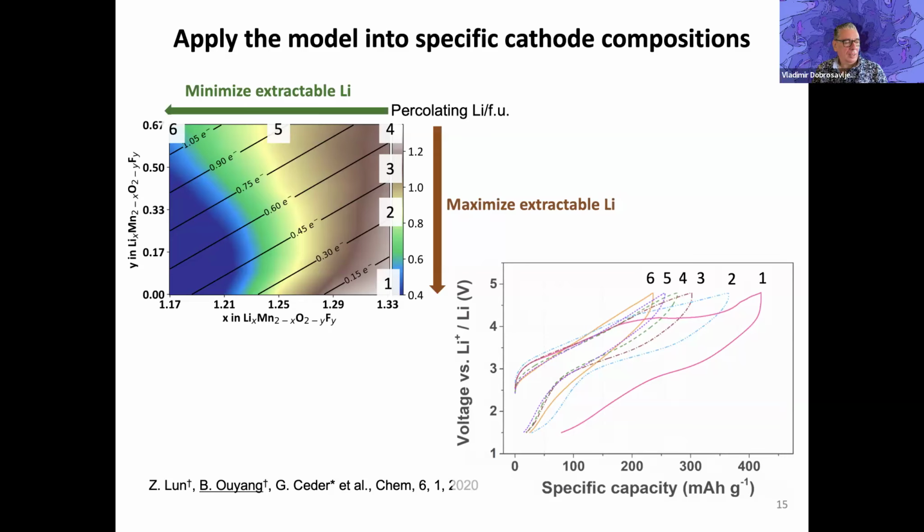Yeah, very good question. So this is sort of the idea of what is a good cutoff of the interactions. First of all, I will tell you how we approach this. We have Ewald summation here. There is a long range term in Ewald summation. So in our Hamiltonian, we automatically have Ewald summation. In that case, it's included. And then we have the cluster interaction radius. In that case, we have some empirical values. It really depends on the performance of the fitting. So if the fitting error converges, we just cut it off there. But physically, we're not so sure. For instance, whether it's going to decay after fourth nearest neighbor, fifth nearest neighbor, we have little idea for now.